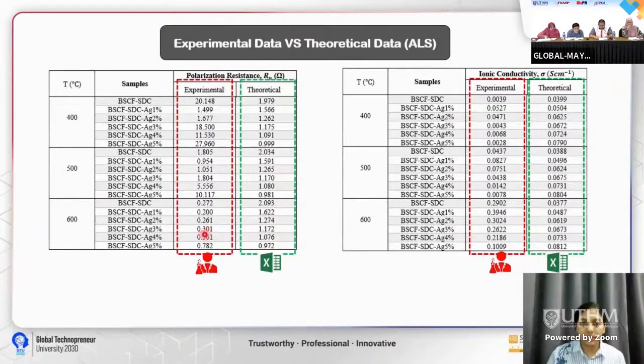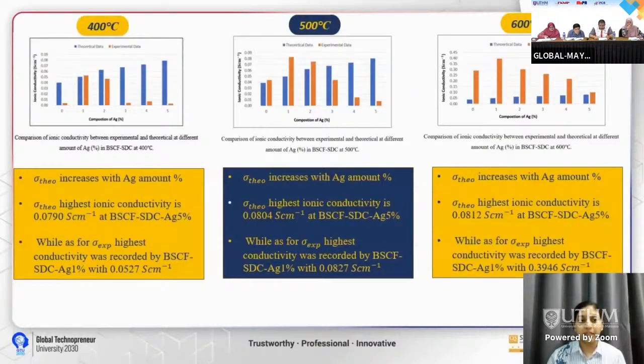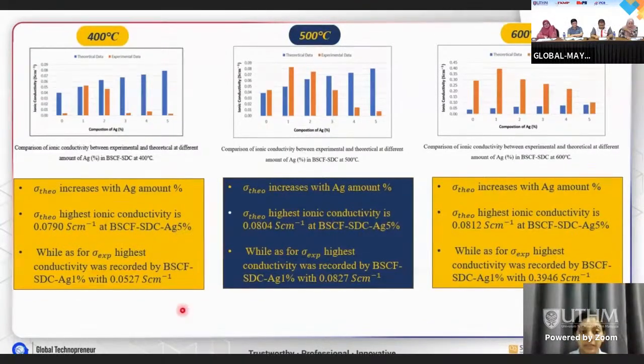So the experimental data is here and it's retrieved from the previous slide. From the data simulated using the ALS model at 400, 500 and 600 degrees Celsius, we can look at the graph and deduce that the theoretical conductivity increases with the Ag amount for all of the temperatures in a very constant manner. The highest conductivity deduced for the theoretical data is at Ag of 5%. And for the experimental data, the highest conductivity was recorded at the BSCF SDC Ag 1%.